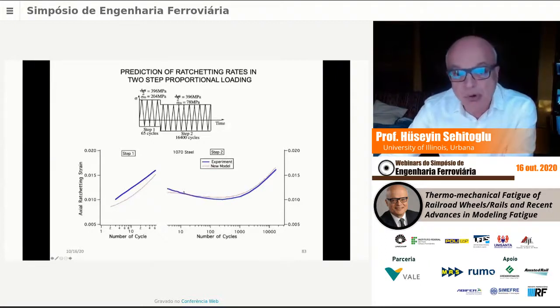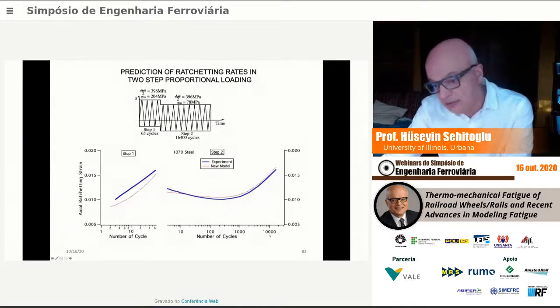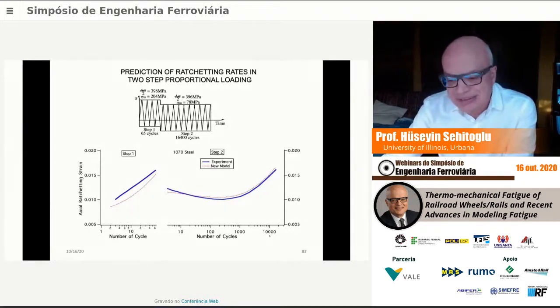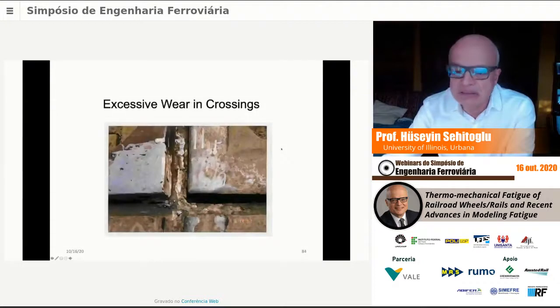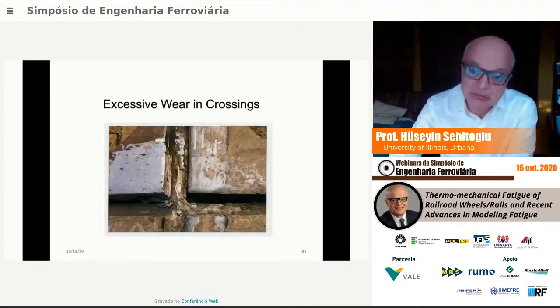The step loading, we're able to capture as well. Step one, step two, the decrease in the ratcheting rate initially, actually going in the reverse direction, and then after many cycles. The key thing for us was to run experiments in the 10,000 cycle region. Previously, people ran tests like 5 cycles, 10 cycles. Well, the 5-10 cycles will tell you one thing, but it's the long-term ratcheting that's important.